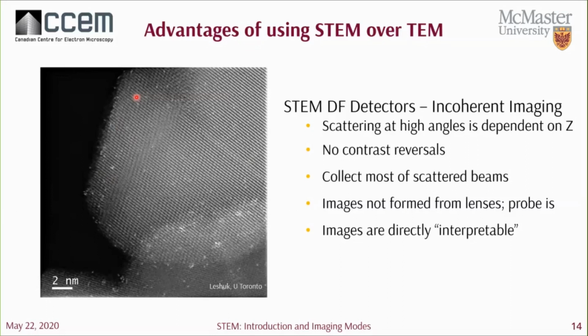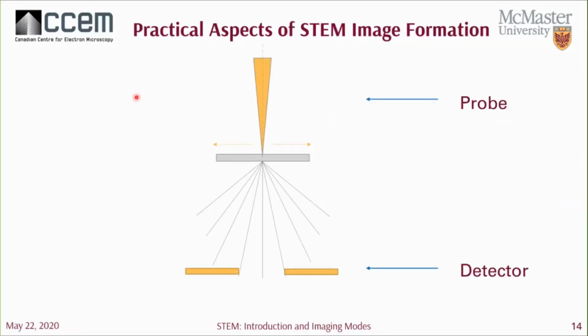But nonetheless, we do use lenses to demagnify and converge the beam into a probe, and so the probe itself does suffer from aberrations. But luckily, there are aberration correctors that we can use to reach a really small probe size. So when forming an atomic resolution dark field STEM image, it's important to consider your setup of the probe and your detector. It's also important to note that forming a good image is dependent on your sample, but I'll discuss that a little bit at the end. So first, let's discuss forming a STEM probe.